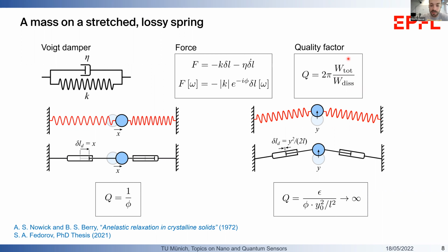And then we get a dependence on the inverse of the square of the amplitude of oscillation. So in the limit where we have a small amplitude of oscillation, the quality factor will diverge, will go to infinity in such a resonance. And we see also the importance of the static strain. Otherwise, we wouldn't even have a properly defined mechanical mode in the transverse direction.